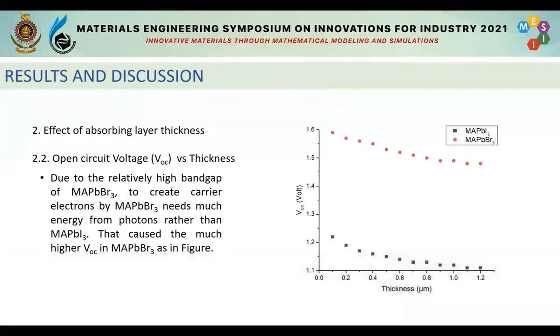When considering the open circuit voltage versus thickness graph, methylammonium lead bromide has higher open circuit voltage than methylammonium lead iodide, because methylammonium lead bromide needs more energy from photons to create charge carriers. The reason for that is methylammonium lead bromide has a relatively higher band gap than methylammonium lead iodide.